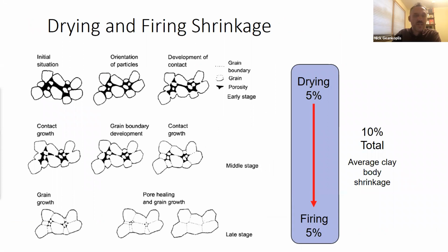So as we continue down the perilous path of ceramics, we can see here a better example of when we go from the wet stages of clay all the way through to the firing stages. I think this slide really helps us visualize that. As I mentioned before, clay shrinks about 5% when it's air dried. It also shrinks about 5% once it's fired to its highest temperature. This, of course, can vary in clay bodies, and some clays shrink as much as 18%. So there's no doubt that Waylande had calculated the exact shrinkage of his clay bodies for the work that he was making and sculpted or prototyped them larger in anticipation of that shrinkage.